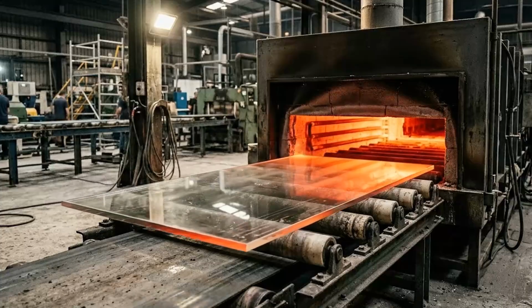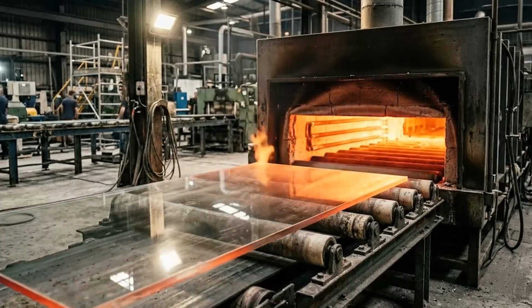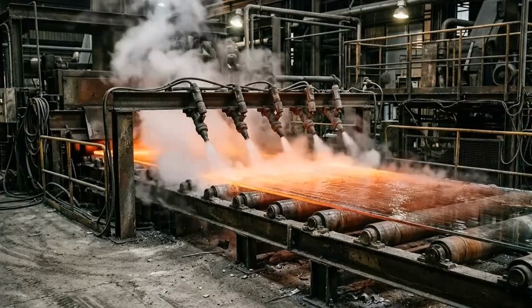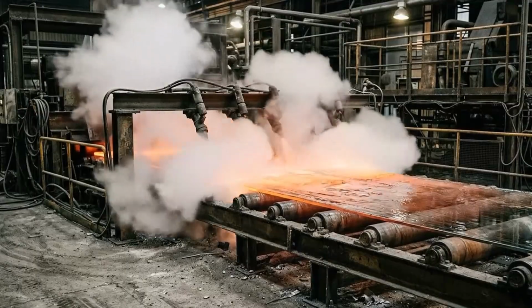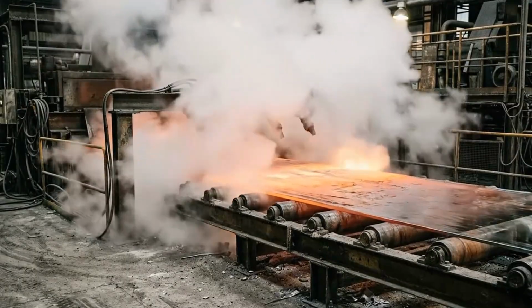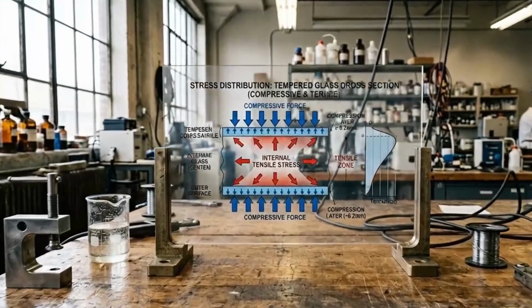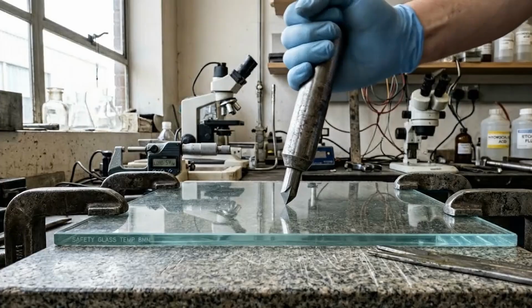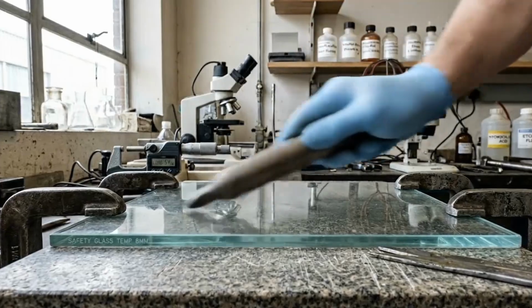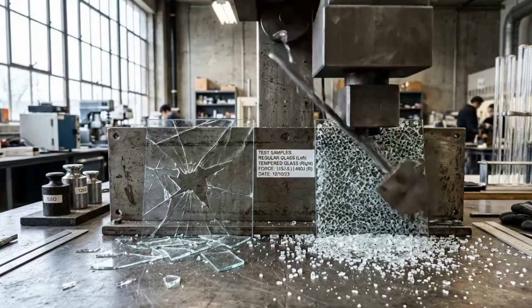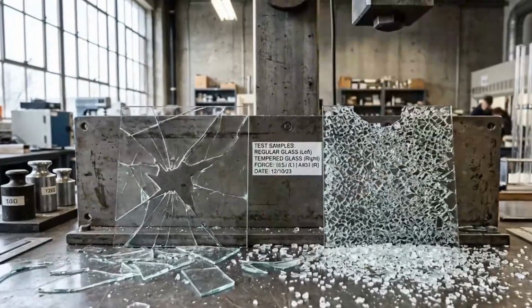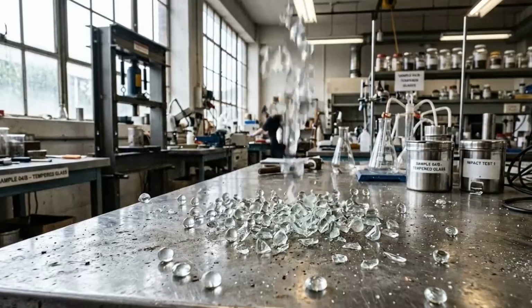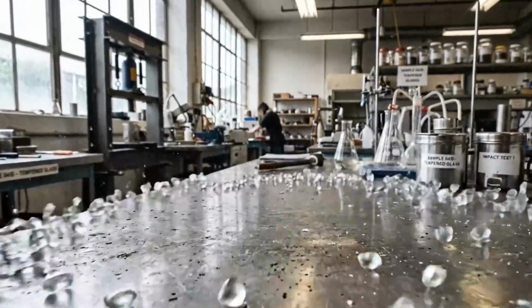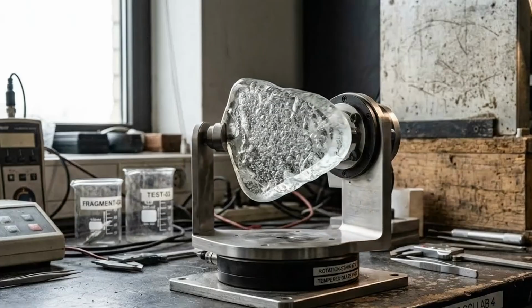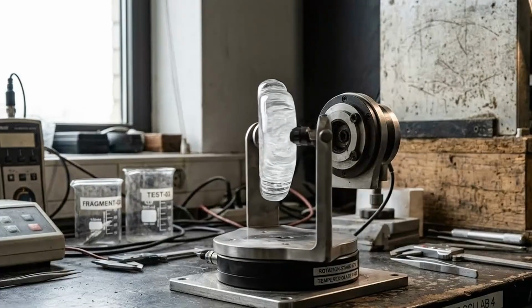Tempered glass, used in car side windows and shower doors, is heated to approximately 620 degrees Celsius and then rapidly cooled on the surfaces. This creates compressive stress on the outside and tensile stress inside. If a crack starts on the surface, it has to fight against that compression, so the glass is 4 to 5 times stronger than regular annealed glass. When tempered glass does break, it shatters into thousands of small, blunt pieces instead of sharp shards, much safer.